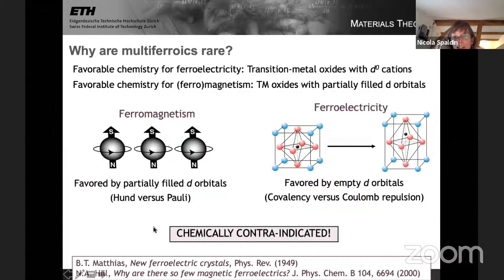I was answering the previous question by saying I was going to keep my D0 cation for the ferroelectricity and use the rare earth as the counter ion for the magnetism. So you're thinking of using the lanthanum as the ion that off-centers. So for example, lanthanum 3+, the empty cation. The bottom of the conduction band would then, I think, be lanthanum d. And so in principle, the second-order Jahn-Teller effect should work, I think. But I think the size would be too big, right? One would have to have a different coordination.